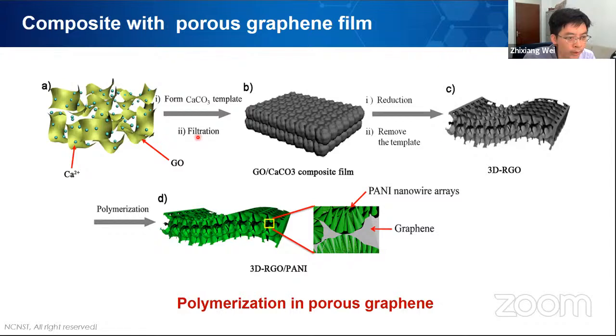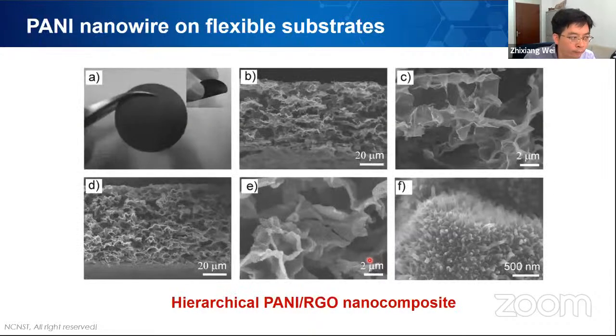For example, we can make self-supported porous graphene by this kind of template, because it's using calcium carbonate template. We can remove this template to get the porous structures, and we can then grow the polyaniline nanowire arrays in these pores. Finally, we can get a film with good shape and good flexibility. This is porous graphene, and then you can grow the polyaniline on the inner surface, and you get this kind of hierarchical structure.